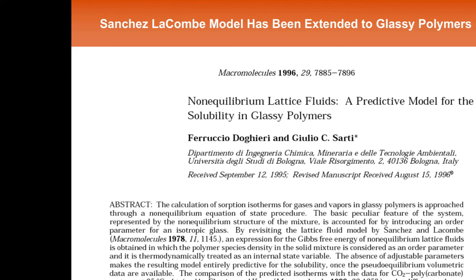And what it says is that at a given pressure of A, if you start to introduce another component in there, what happens to the concentration of A in the polymer? It goes down, right? Because if you start to increase the partial pressure or fugacity of B, this term in the denominator starts to become important. This overall Langmuir term is reduced, and then the overall sorption of A in the polymer is reduced. And that reflects the competition of A and B for the fixed number of non-equilibrium excess volume sites or fixed number of Langmuir sites. And likewise for B, equation 6.